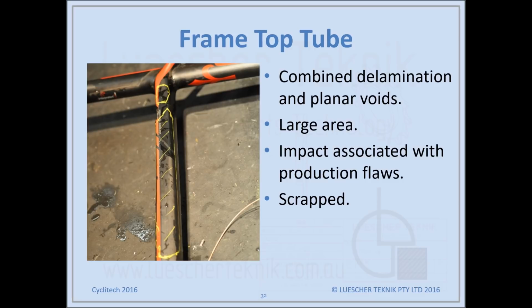Another one that we have is a combination of an impact and planar voids and porosity. In this case, the top tube was impacted, but because the laminate quality was quite poor with planar voids and porosity, basically the entire top tube, the whole face of the top tube, delaminated. That was beyond a practical repair, and the bike was scrapped. So it's an example of where you've got production flaw issues combined with an in-service impact.